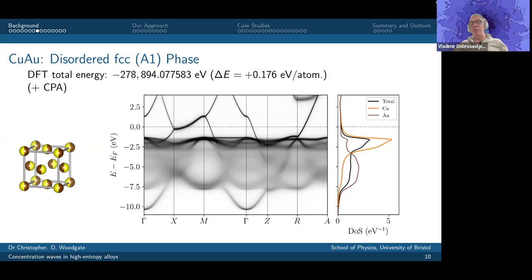Right, it's incredible how the mixing of the bands is confined to this strip where you have many bands, and then at high energy or even near the Fermi energy, there is very little mixing and broadening of these bands, right? Yeah, it is interesting. The reason that happens is that the SP states, the more dispersive, free electron-like states, are fairly similar for both copper and gold, and the real difference is in the D bands, which is this band of smeared out states in the middle here. Essentially what you can see on the right is that copper has a fairly narrow 3D band, whereas gold has a wider 5D band, and so the reason the smearing is so heavy in the middle is because of this mixing of the 3D and the 5D states.